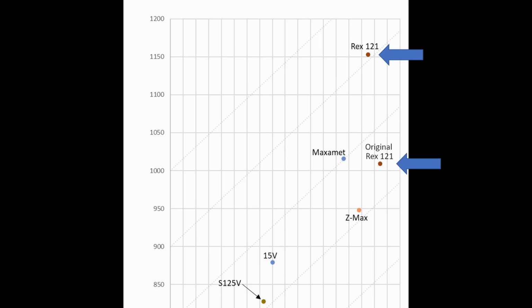I think also for some people, a sharpening stone's a sharpening stone. Don't tell me all that nerd stuff about abrasive. But if you're compounding that issue, if you're using a soft abrasive that's not sharpening all the features inside the steel... So what we ended up doing is we just heat treated a whole new blade using a different heat treatment, where we attempted to minimize the retained austenite, and then it sharpened up beautifully.